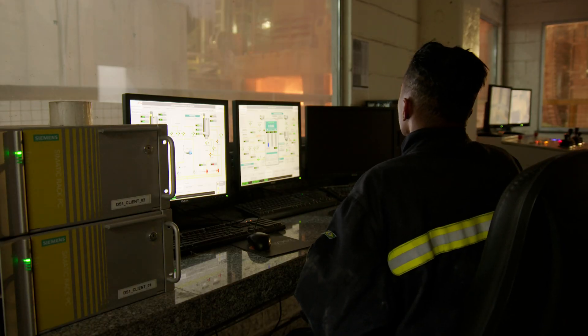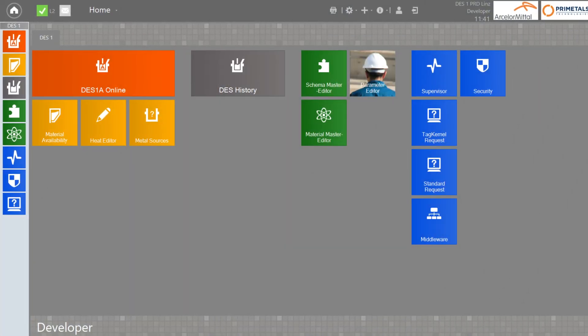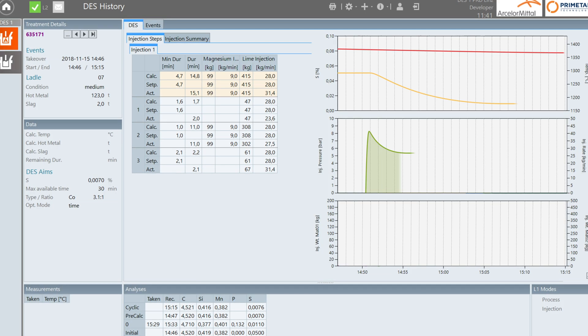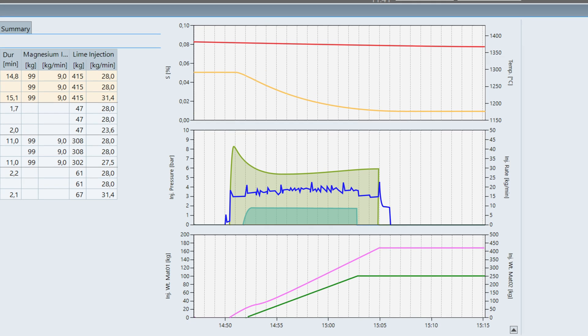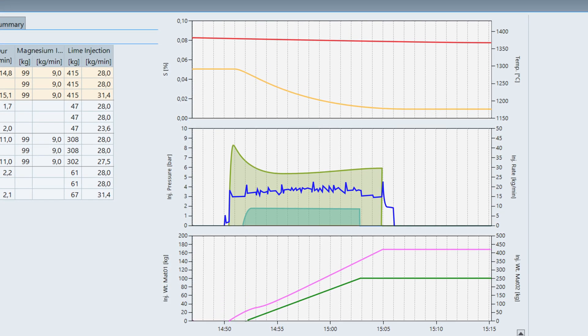The new desulphurization process is controlled by advanced Level 1 and Level 2 automation systems. They are capable of making highly accurate predictions, with an average deviation of the measured sulfur content from the calculated values of less than 5 parts per million. The automation systems are also a key factor in achieving a sulfur content of less than 50 parts per million.